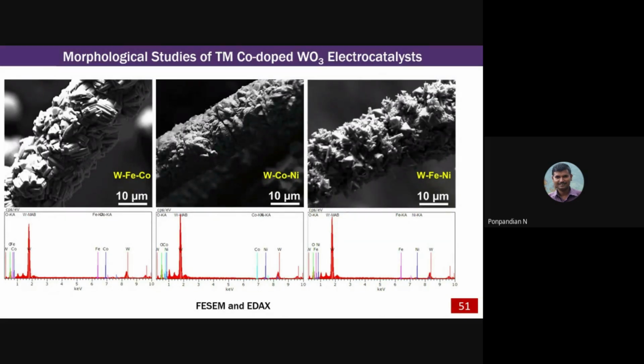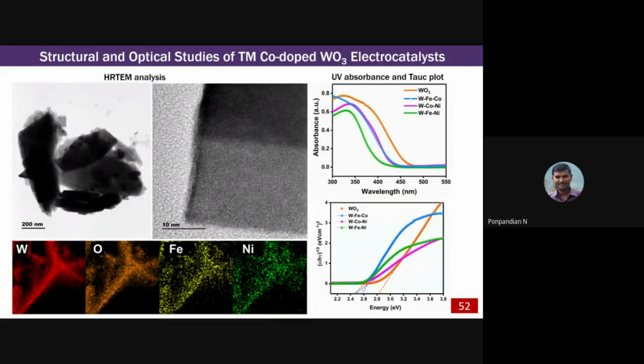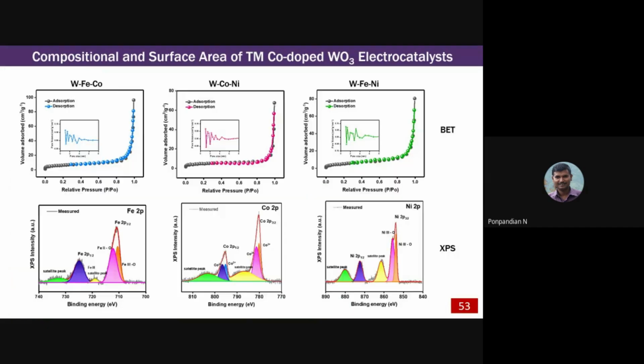We got the best electrocatalytic activity for the iron nickel sample, because you all know that nickel is a very good electrocatalyst, and when it is joined with iron it gives much improved electrocatalytic activity. This is a transmission electron microscopic image of this transition metal co-doped material. This is the surface area analysis of this material. The surface area here is much higher compared to the other co-doped samples. In the case of iron nickel, the surface area is maximum, and in that way the catalytic activity of that material is also maximum.